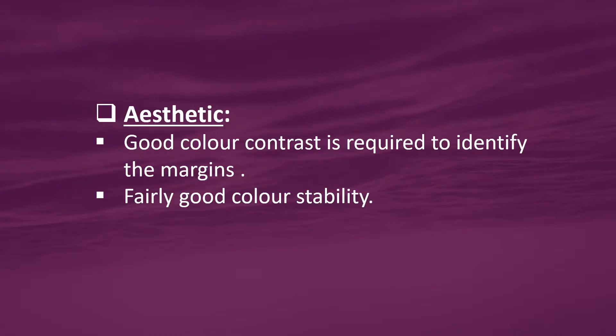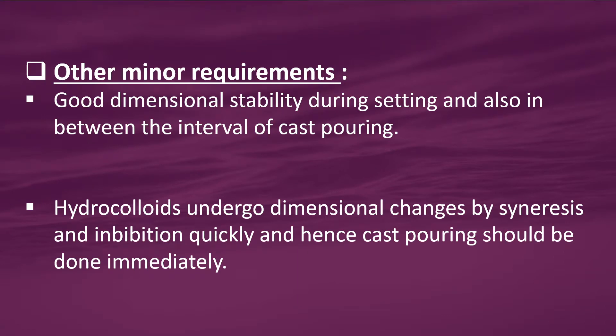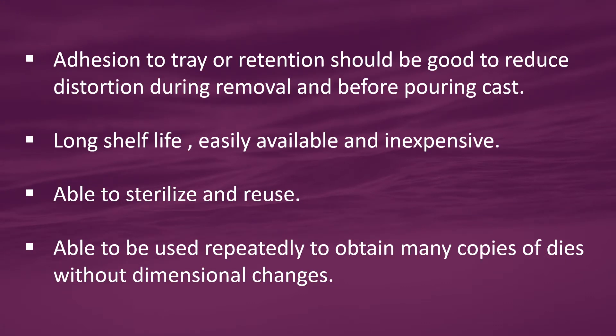Next, aesthetic: it should have good color contrast to identify the margins and fairly good color stability. Other minor requirements include good dimensional stability during setting and in the interval before cast pouring. Hydrocolloids undergo dimensional changes by syneresis and imbibition quickly, so cast pouring should be done immediately. Adhesion to the tray or retention should be good to reduce distortion during removal and before pouring the cast. It should have a long shelf life, be easily available, and be inexpensive. It should be sterilizable and reusable, and able to be used repeatedly to obtain many copies of dies without dimensional changes.